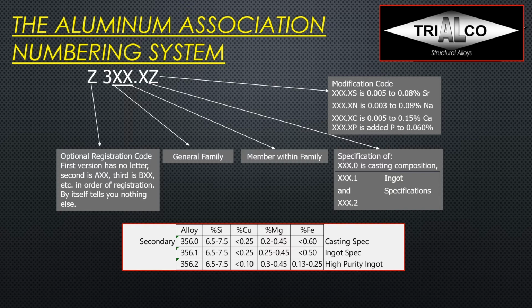so silicon doesn't really change. You don't pick it up, you don't lose it. Always the same, whether it's in the casting or in a normal or higher purity ingot. Copper you might pick up, so the higher purity, the 356.2, has a lower copper than the casting specification. Magnesium you will burn off. Again, the ingot specification is higher in magnesium than the casting specification. Iron, the opposite, you will pick it up, and therefore the ingot specification is lower than the casting specification.